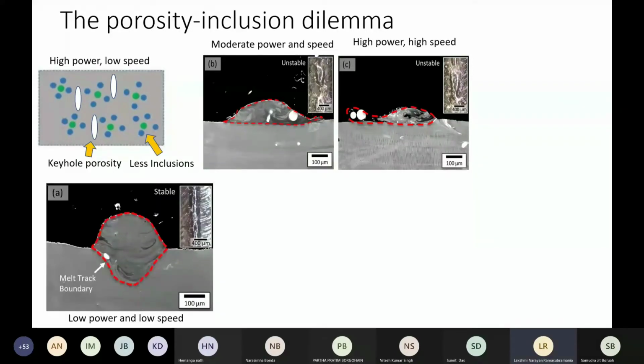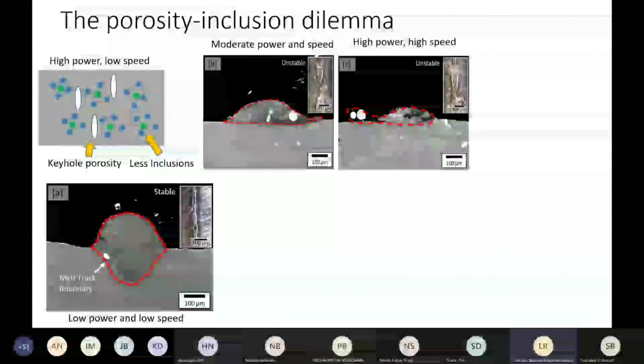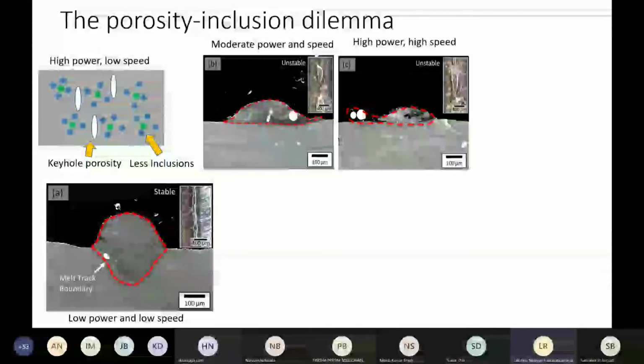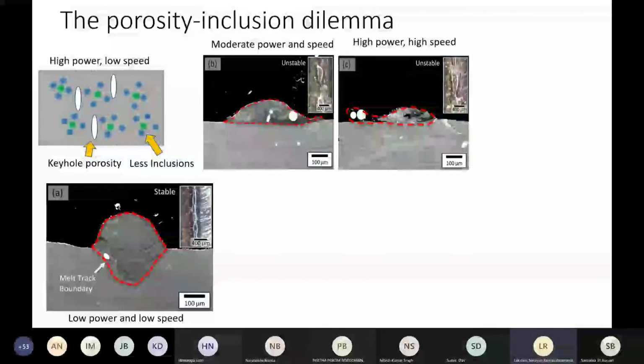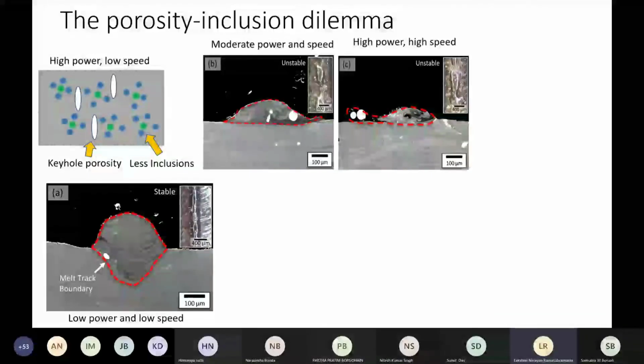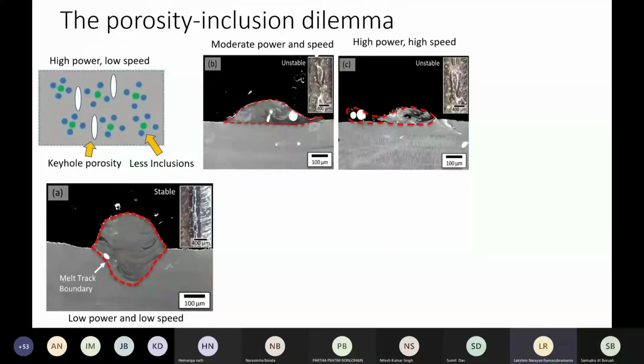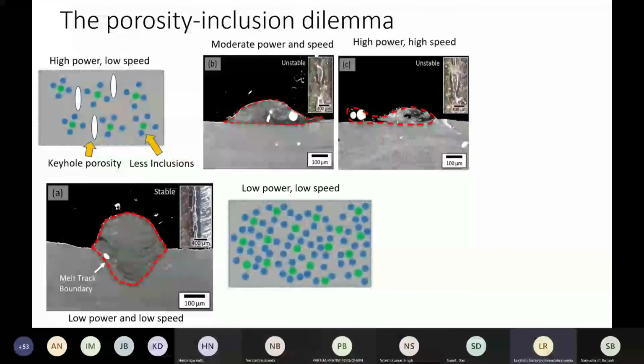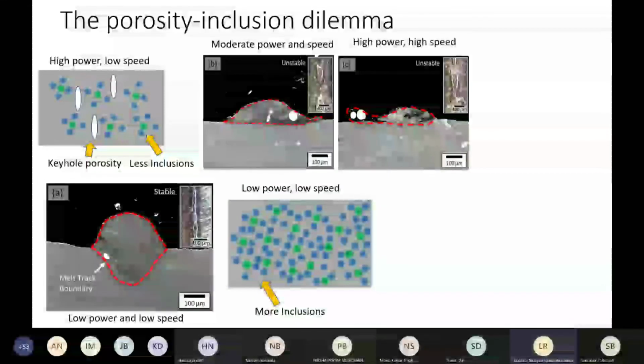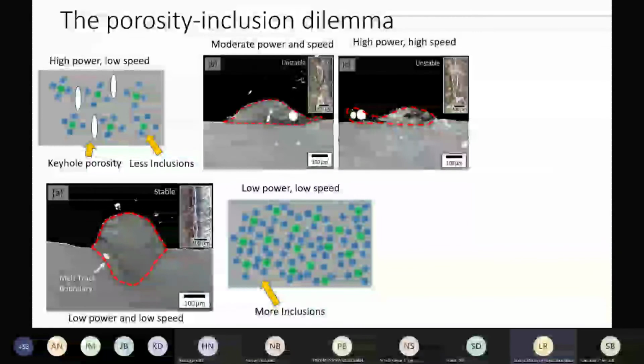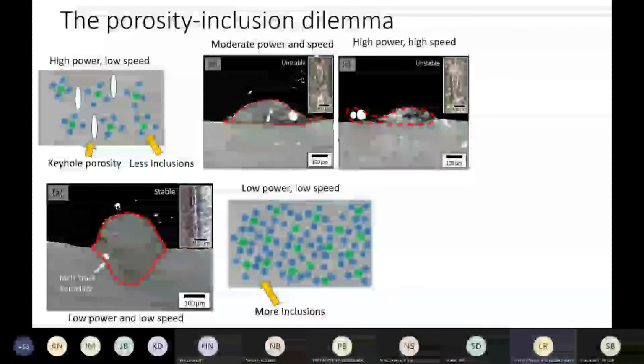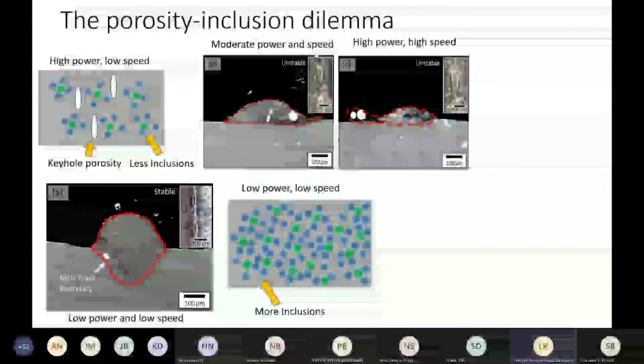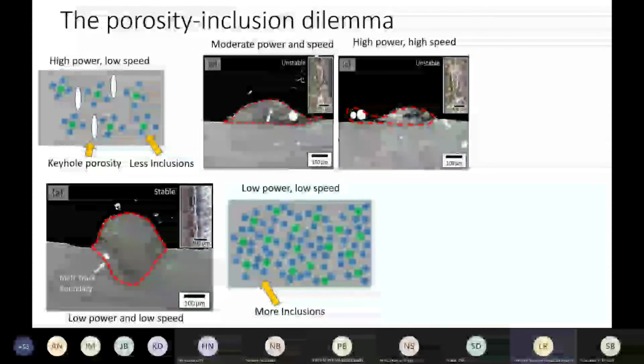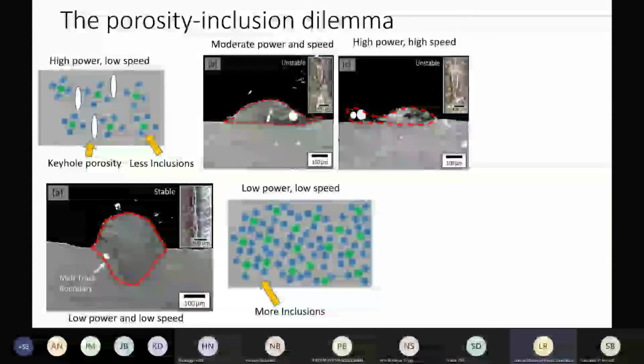What essentially you can do is use lower power and very low speed. Of course, that will result in lack of fusion, but then you have some window. You can in fact keep it reasonably low power and reasonably low speed to make sure that the melt pool looks very nice. But the problem with low power and low speed is that you will have more inclusions because you're not inputting more power for the niobium to melt. Niobium has intrinsically a higher melting temperature than titanium. So titanium melts first and niobium sometimes remains as inclusions.